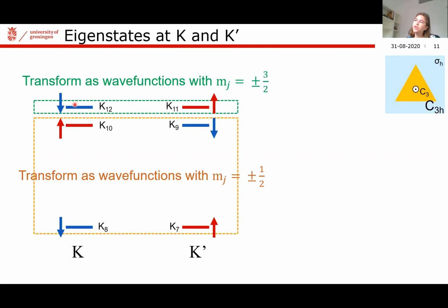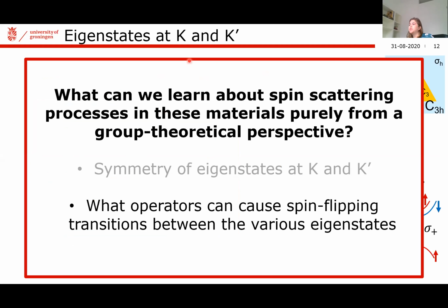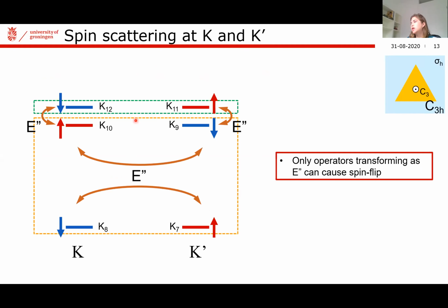I need to tell you that the ordering of these states, I think also most of you know, depends on the particular transition metal dichalcogenide that you take into account. And the ordering that I have drawn up here actually corresponds to tungsten disulfide or tungsten diselenide. But although the ordering does depend on the particular TMD, the symmetries do not. So now that we have these symmetries, what can we learn about the spin flipping transitions? Right? If we just look at a product table for the C3h point group, we can figure out that only operators that transform as E double prime can actually cause spins to flip in these materials.